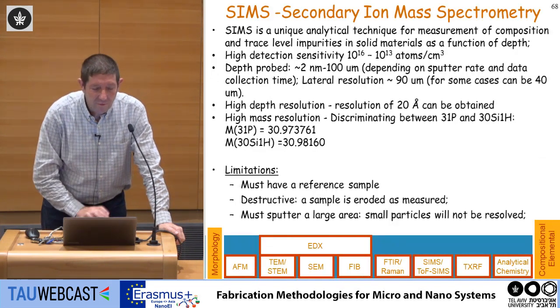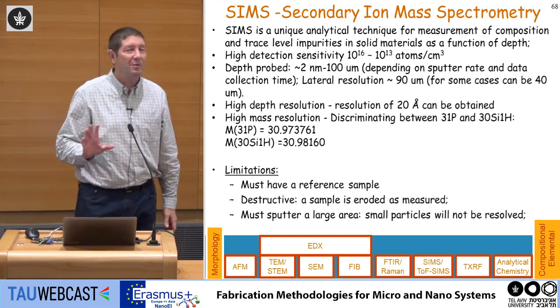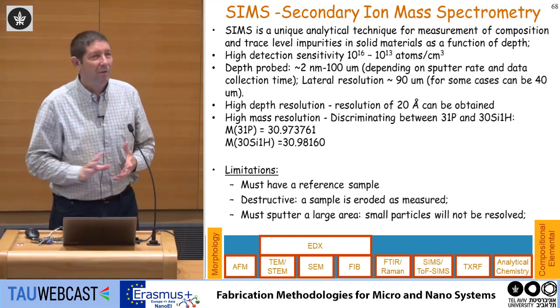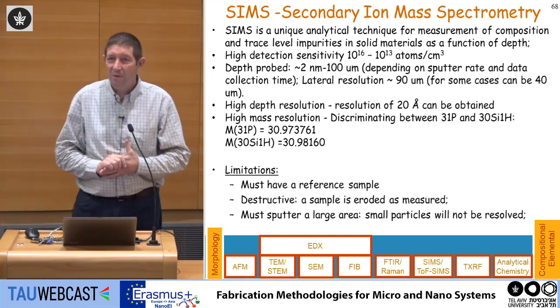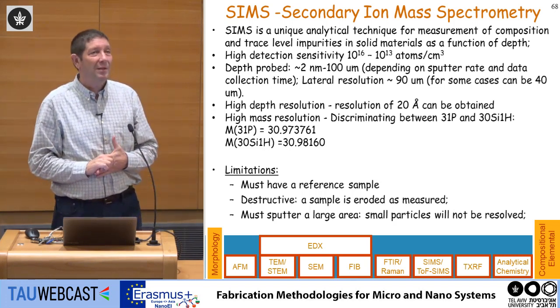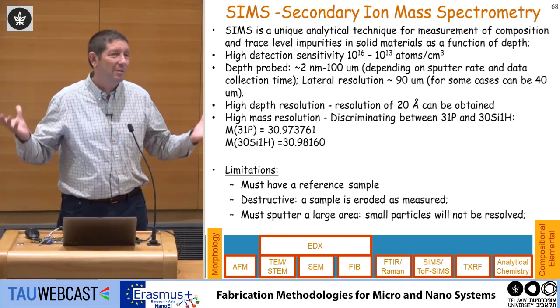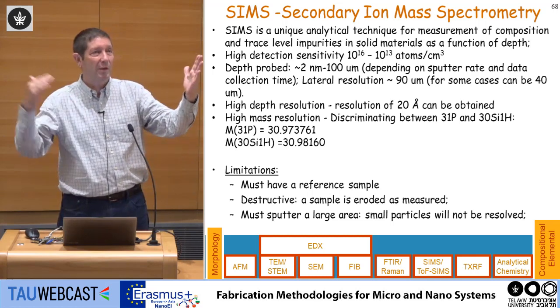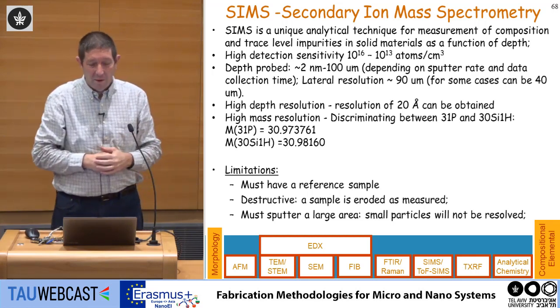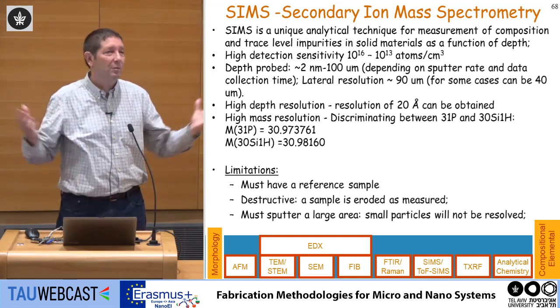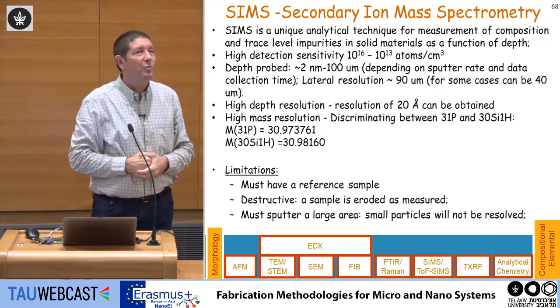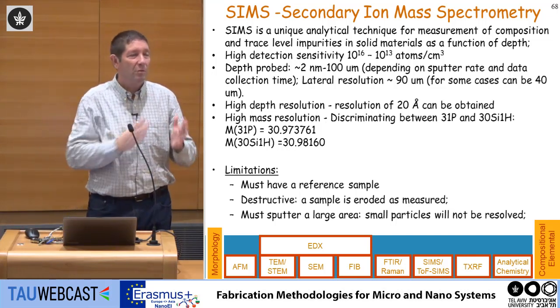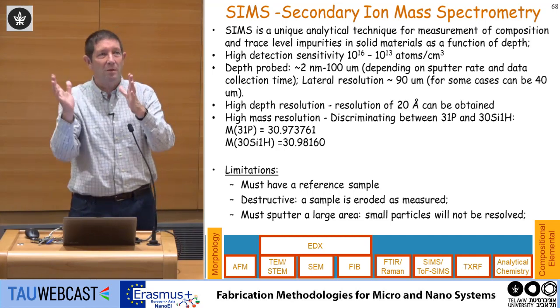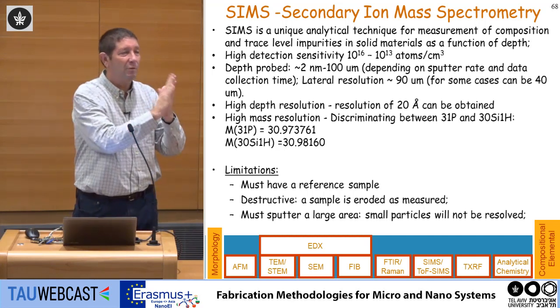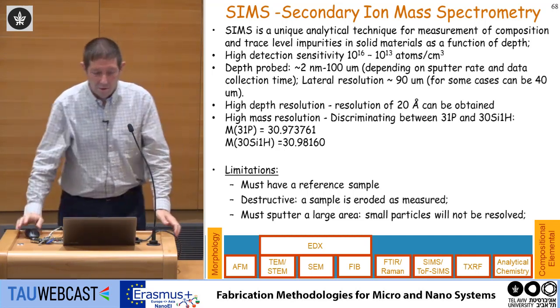Next technique is SIMS. It became very popular. One of the reasons is that it's very simple, and second, it's extremely sensitive. You take your substrate and you hit it with ions, and you look at the ions that you sputter, and you look at their composition. You remove material and measure the amount of secondary ions.